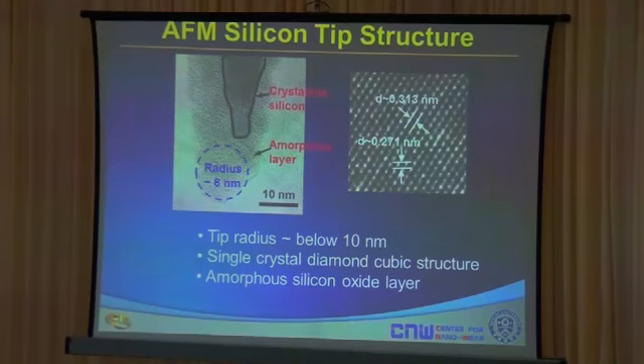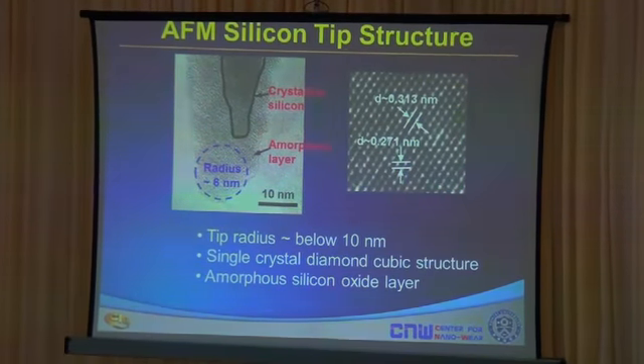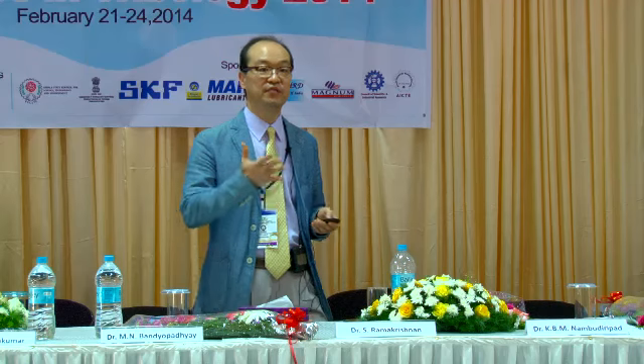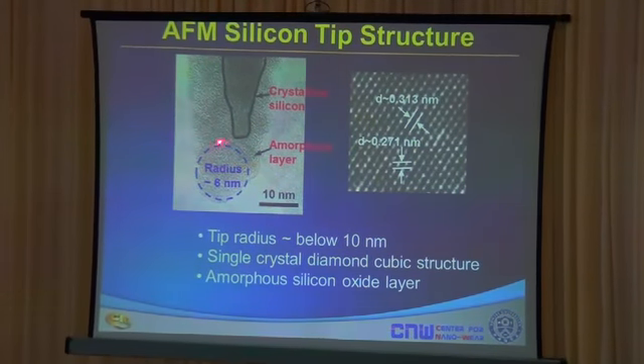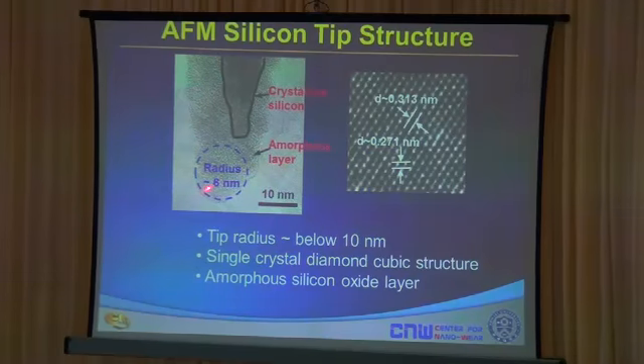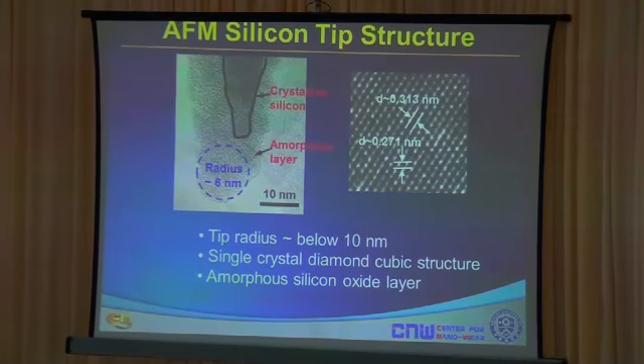So what we first looked at was the mechanism of AFM tip wear. These tips are made of silicon because of ease of manufacture using photolithography techniques. But actually, it's not silicon that is touching your specimen. Because it's exposed to the environment, the surface of the silicon tip is covered with an amorphous layer of silicon oxide. And actually the silicon oxide is in contact with your specimen. When you rub them against each other, it's this amorphous layer that's being worn out. We can look at the TEM image of this amorphous layer, and it's well represented. The radius in this case of this particular tip end is about 6 nanometers. Typically, the tip radius is on the order of about 10 nanometers to tens of nanometers.